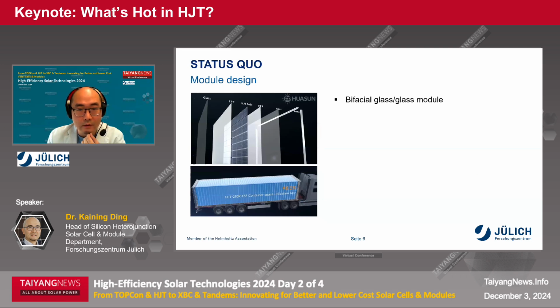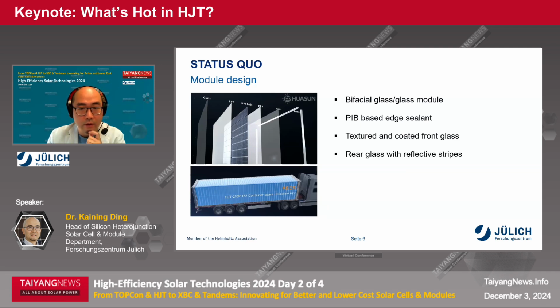And on the module side, the module design has, in my opinion, consolidated a little bit more. So it's more common to use a bifacial glass module. And PIB-based edge sealant is a must. So these two things are important to protect the module from moisture. And the front side glass is textured and coated, and the rear glass has these reflective stripes between the cells to increase reflection into the solar cells.